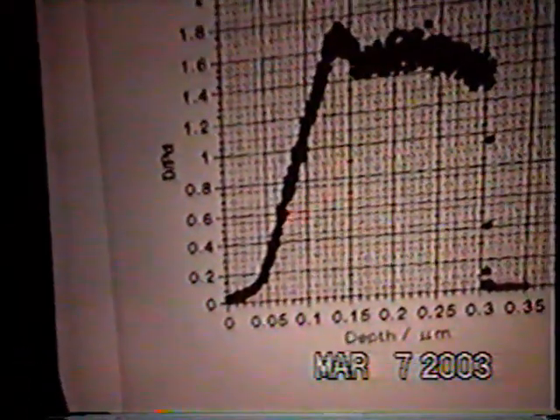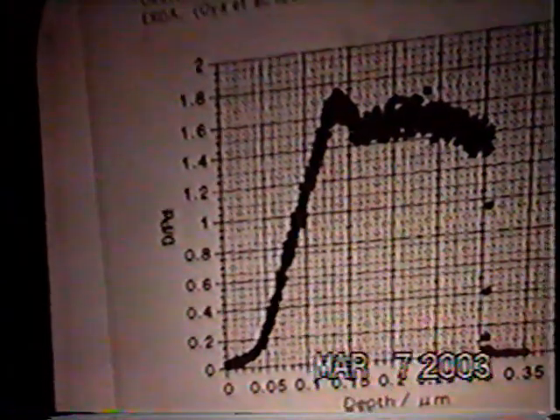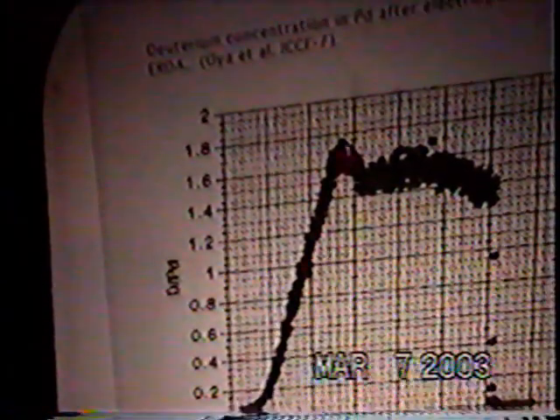So let's go back to the first one. The surface composition is difficult to measure, and the numbers that you see quoted are the average composition, not the surface. The surface obviously has a much higher composition than the average. This is one study of the surface as a function of depth. You can see there was a certain amount of surface deloading here, but the composition is as high as 1.7.